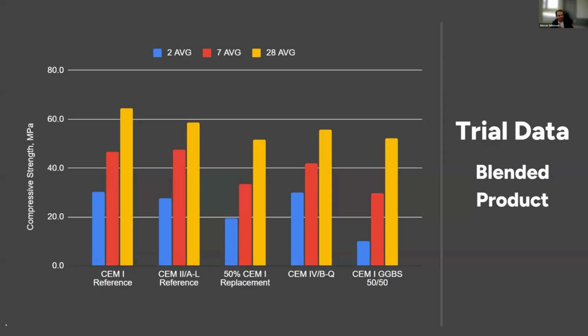We then developed a blended product. So compared with the 50% CEM1 replacement, we've developed a CEM4B, which is 50% clinker co-ground with 50% calcined clay. And the big difference there, we're seeing a much better strength development in 2 days. So it's interesting to see the difference between a blended product and a co-ground product and how that actually performs in reality and in practice. Again, seeing much more preferable early strength development compared with a GGBS blend.